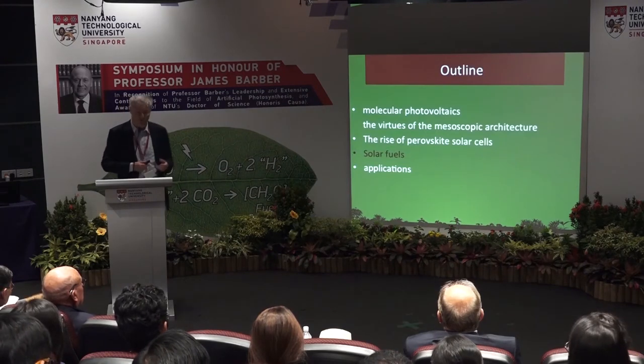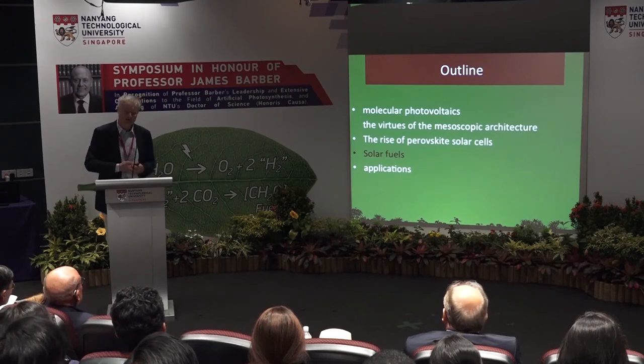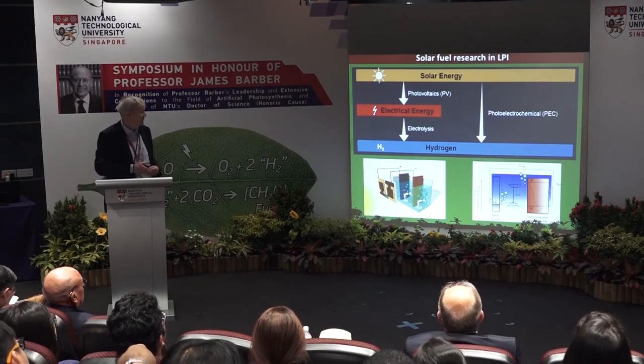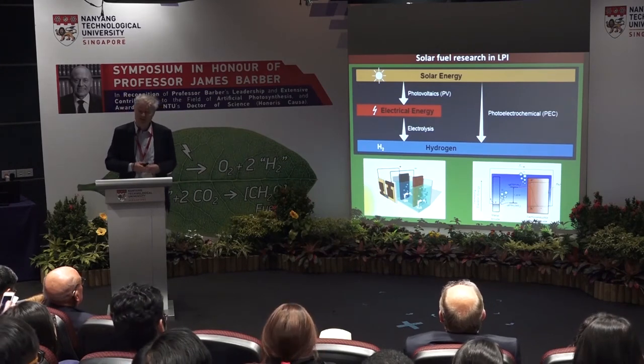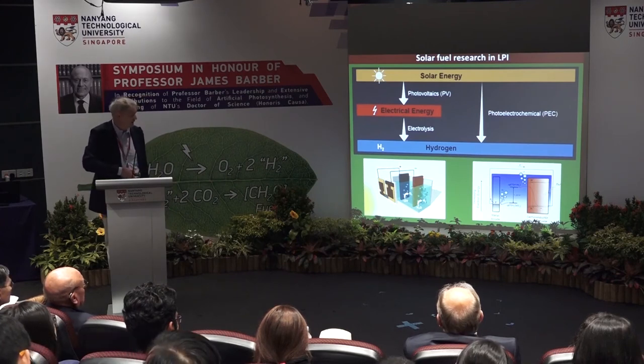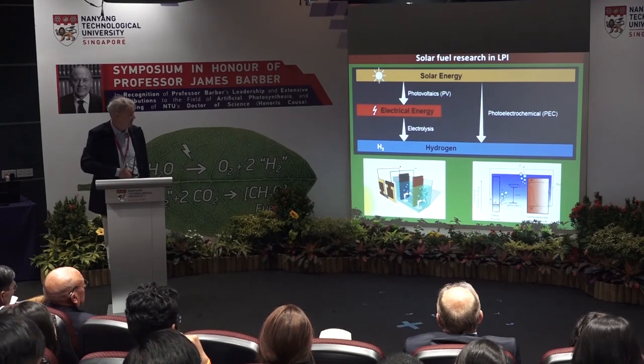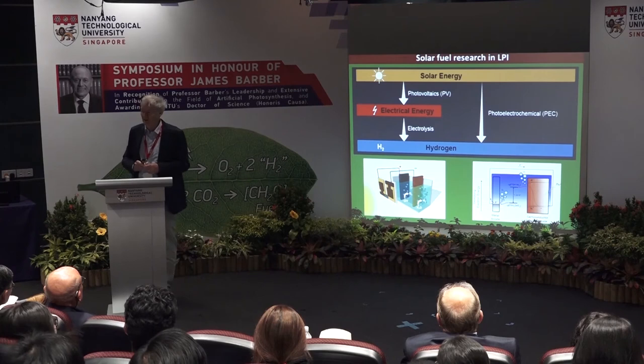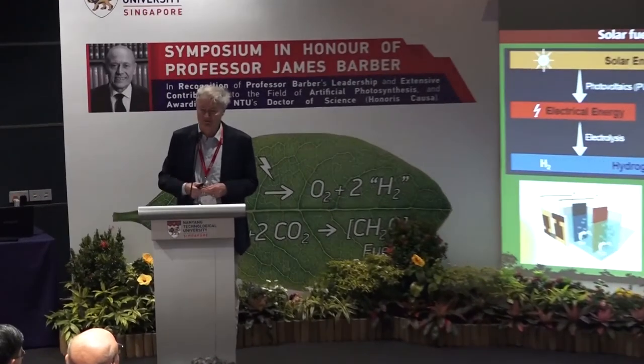We have been using these perovskite cells, as Jim mentioned, in a tandem configuration. I want to talk about our solar fuel effort. We have been working on the combination of photovoltaics with catalytic electrodes, and we are also strong defenders of photoelectrochemistry — where we excite the material itself to generate fuel. For example, a P-type electrode where excited electrons make hydrogen from water — cuprous oxide does that — and then the positive charge oxidizes water to oxygen. In all these cases, it turns out you need a tandem, like in nature: nature has two photosystems, and a single photosystem is not enough to get water cleavage or CO2 reduction going.